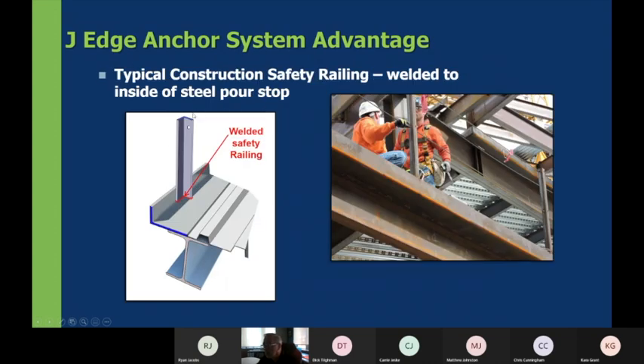This is the part that I was promising you about the handrails and the advantage that J-Edge has. Now this is a typical bent plate detail at the edge of slab, and this is what they have to do for temporary safety railing for construction in the field. You can see that they have to weld an angle to the inside of the bent plate. What happens to the angle whenever they finish construction? It simply gets zipped off and cut level with the slab, and that introduces some re-entrant corners into your nice slab where cracking can originate from. And think of all the wasted material associated with this cutoff system.